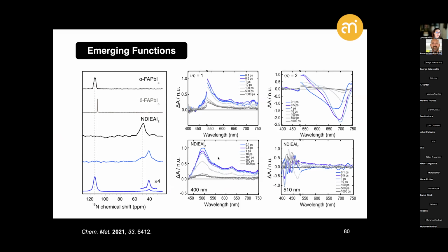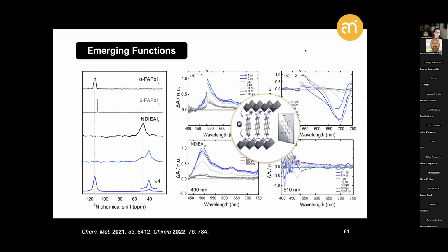can photogenerate these stable radical anions that could not be accessed at higher wavelengths, for example, at around 510 nanometers, but were used, in fact, to excite the perovskite samples containing NDI, nonetheless showing the presence of radical anions that results, in this case, from the exchange between the inorganic and the organic phase, opening a path for more functional layered hybrid perovskites. These systems still face a number of challenges that need to be addressed for their application in photovoltaic devices and other optoelectronic functional systems, but they conceptually are opening an interesting path for further utility of layered